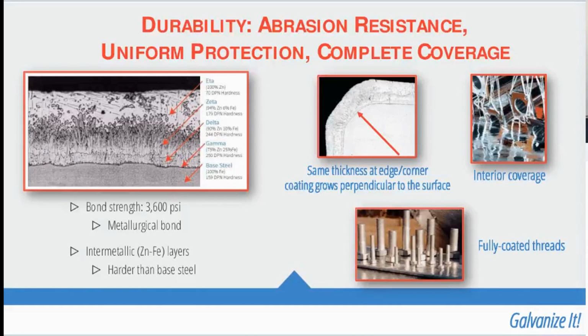Another aspect of hot-dip galvanizing is its proven durability. Hot-dip galvanizing provides abrasion resistance, as the coating is mostly comprised of zinc and iron intermetallic alloy layers, and these alloy layers are actually harder than the base steel itself. And because the coating is formed by a metallurgical reaction, the coating actually grows perpendicular to every single surface along the part and at the same rate, meaning that you also achieve complete and uniform coverage over surfaces such as edges, corners, threads, and generally just interior surfaces.